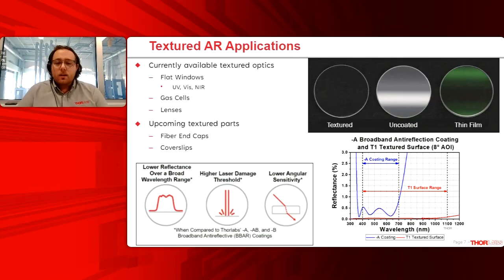So you can see here, specifically in the bottom right, the reflection over wavelength, and our textured substrates have extremely broadband performance, and they do have that lower angular sensitivity. This is because they are not relying on a quarter wavelength condition needing to be maintained. Additionally, because these pillars are etched directly into the UV fused silica, they can withstand much higher laser damage thresholds.